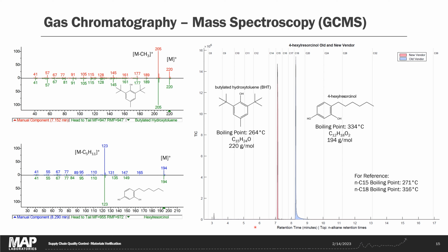So as the materials exit that GC column, they get impacted by an electron beam that fragments the molecules, and those fragments are analyzed by a mass spectrometer to give us the size to charge ratio. We can see that we have two peaks here. The new vendor was exiting the column at about 7 minutes. The old vendor was exiting the column at about 8.3 minutes. This is pretty consistent with the expected boiling point difference between butylated hydroxytoluene and hexylresorcinol.